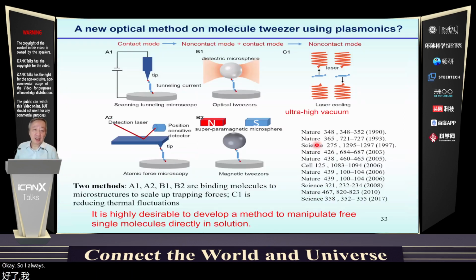Okay, so I always like to go back to the starting point, or to get a comprehensive picture of a new field. As we can see, in fact, we have found that there have been 5 methods for this molecular tweezer. However, unfortunately, because it's so difficult to control or track a very small molecule, people use either an AFM or STM tip for binding the molecule. Then they make some manipulation. They can also use, this is AFM, this is STM, and this utilizes a magnetic field to control it. And we are most interested in this tool because it's related to optical trapping.